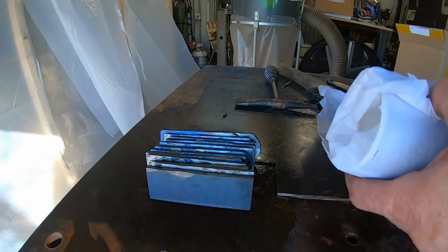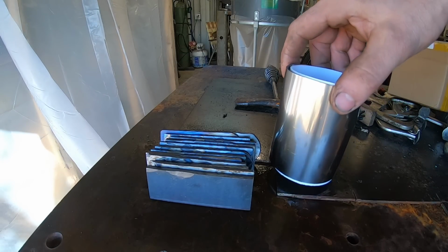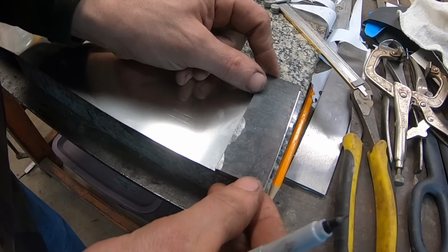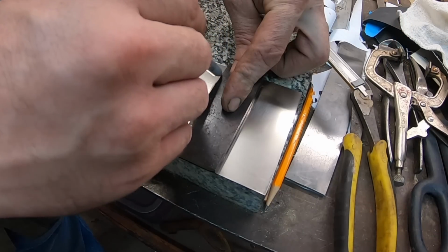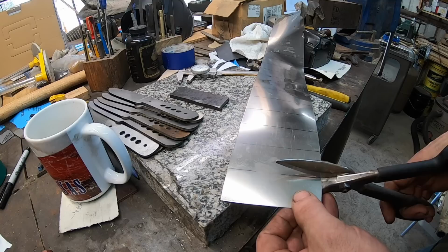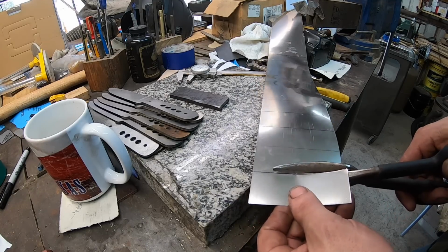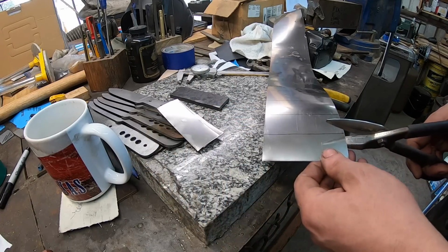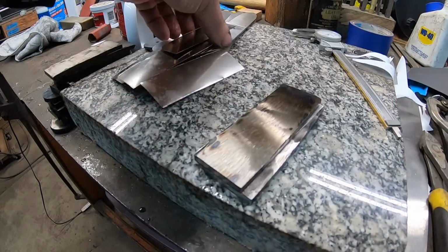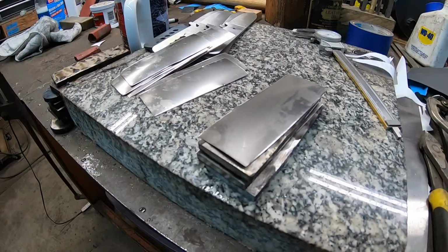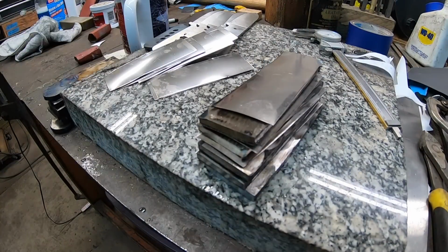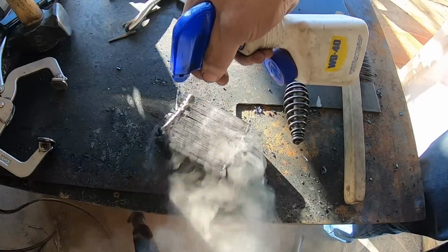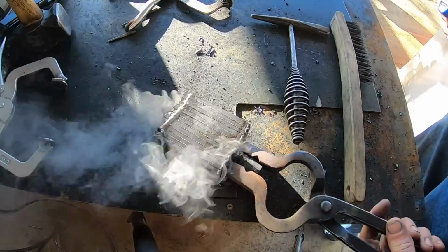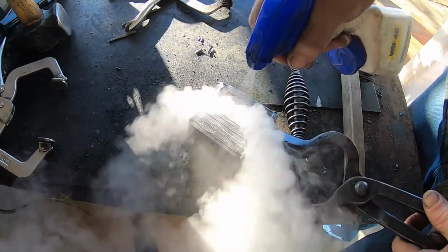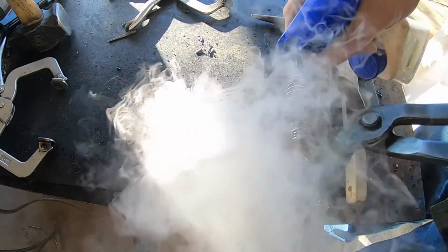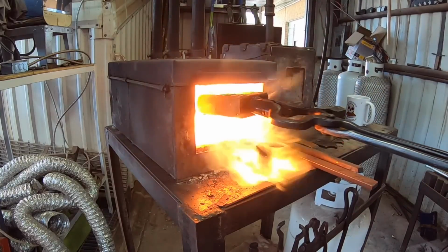Next, I have a roll of pure nickel, and it's about 0.2 millimeters. I'm not sure what that converts to in inches, but it's thin, I know that, and it should give us a nice contrast, because the nickel is very bright compared to even the medium or lower carbon steel like this 1045. Of course, the nickel content in your 15N20 steel is what gives it the contrast against the other carbon steel that you would use in a typical pattern welded billet.